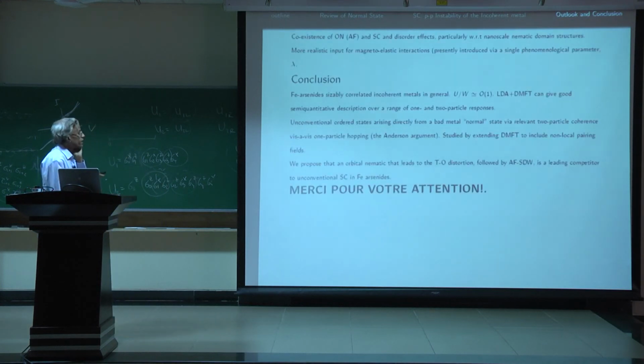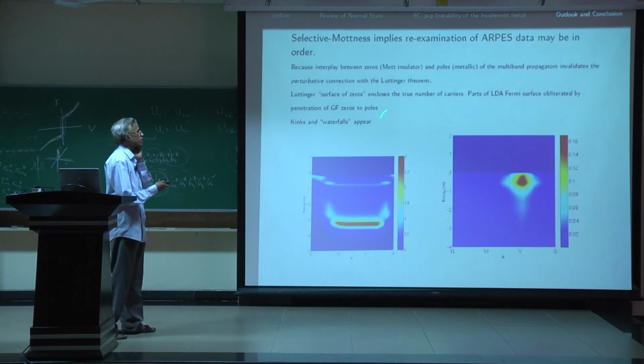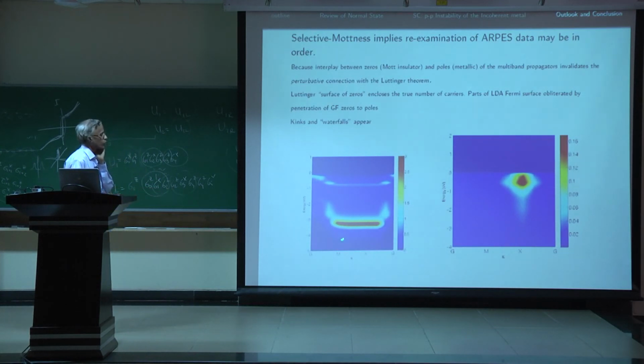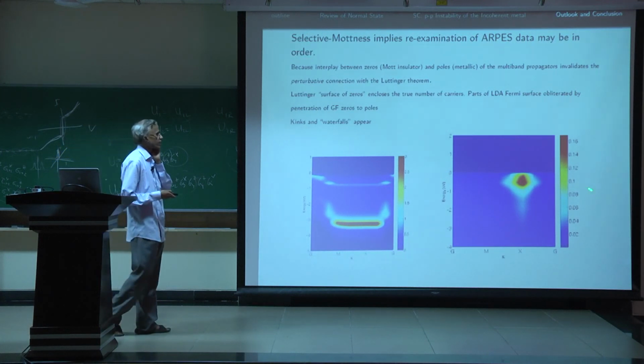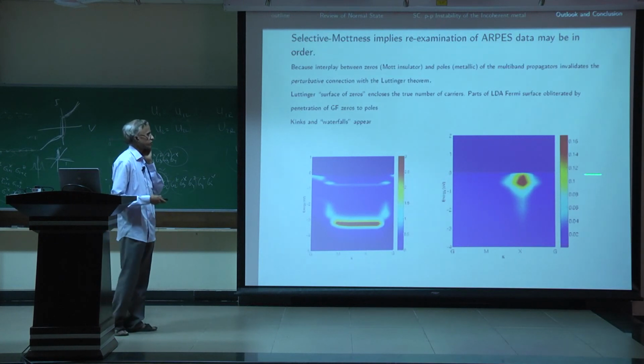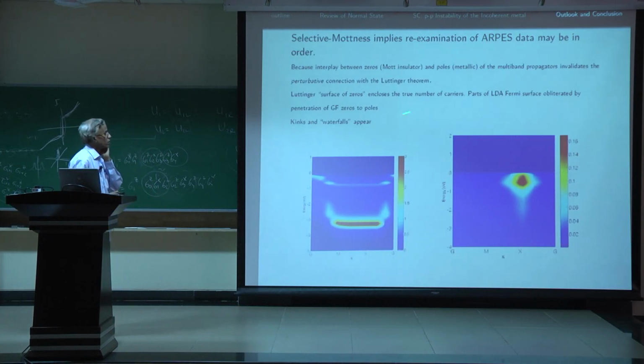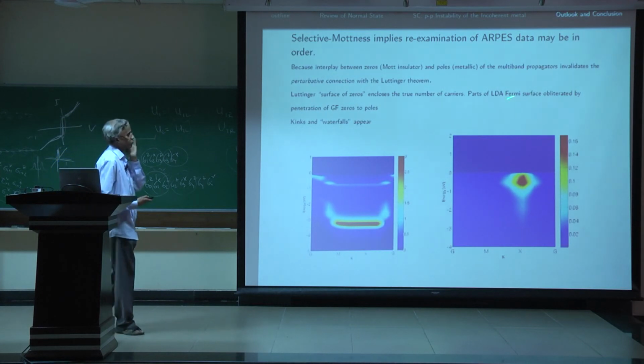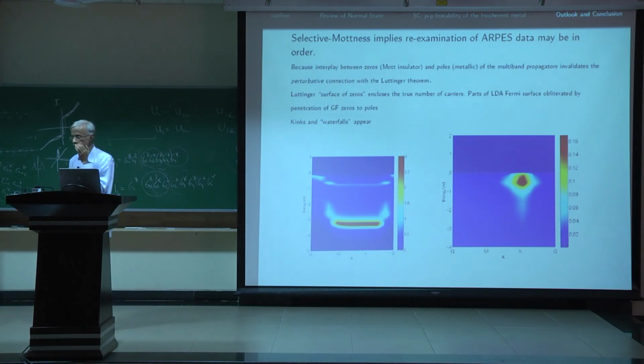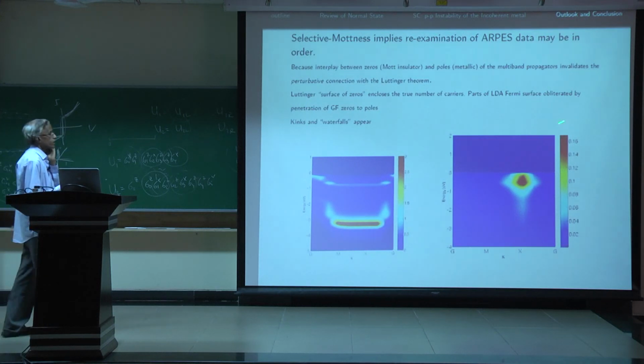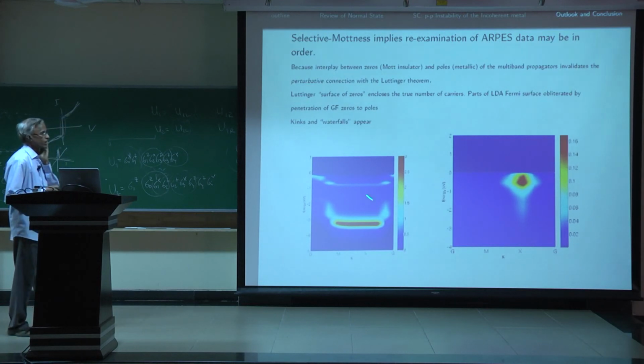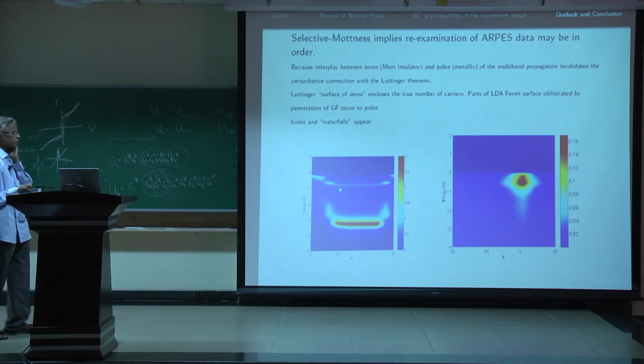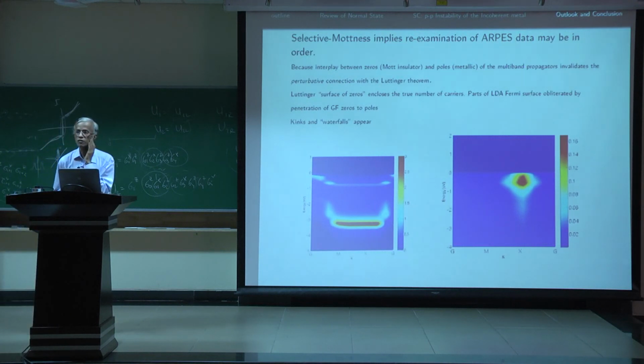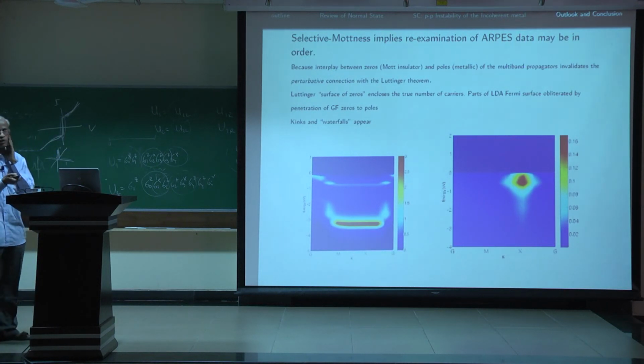Right, so that's the message, and this is basically what happens in a simplified model. So what you see is basically in the Mott localized sector you see appearance of kinks and waterfalls, while in the metallic sector you see basically total loss of quasi-particles. So if this is true, then if the question is asked as to how does an antiferromagnetic metal arise from such an incoherent metal, it may involve the topologically reconstructed Fermi surface aspect that is associated with selective Mott physics. Okay, so I thank you for your attention.